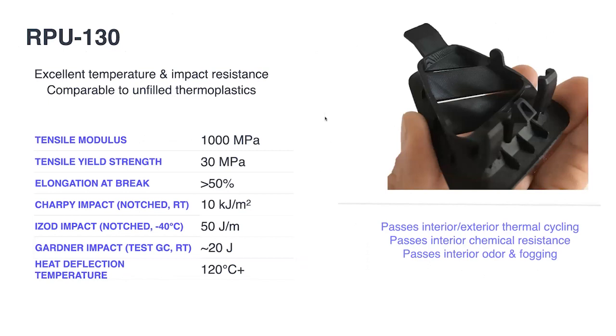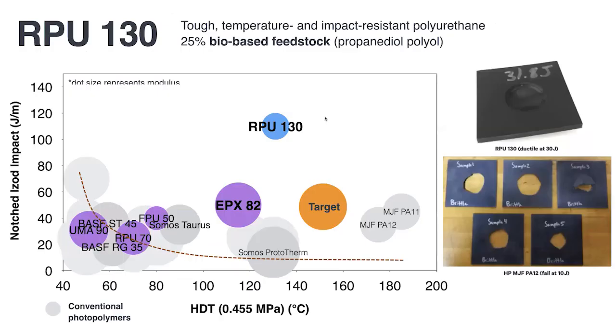It's got impact strength that's like a thermoplastic. In fact, here's a plot of notched Izod impact versus heat deflection temperature, close to a TG kind of parameter. And these are placards made by selective laser sintering. And then you hit this in the center with a pendulum or a ball and it fractures. But you do that to this material and you see ductile deformation. This is a really amazing material that's got a high impact strength, and it's made out of heavily a 1,3-propane diol polyol, 25 weight% of that in this material.